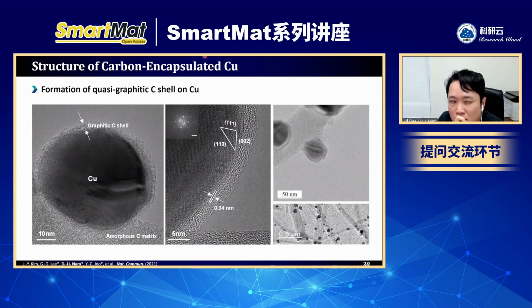I think so, because in this work we didn't do a thickness study of this carbon shell for selectivity. We focused on the carbon shell preventing reconstruction, and also being very effective against copper dopant penetration. So we focused on that, but I totally agree, because the carbon shell thickness can also affect the selectivity of the copper, because the carbon shell can also affect CO2 adsorption on the copper, I think. But in this paper, we couldn't do that kind of study, but I totally agree. Yeah, that will be very effective for catalyst design. Yeah. Oh, yes. Thank you.